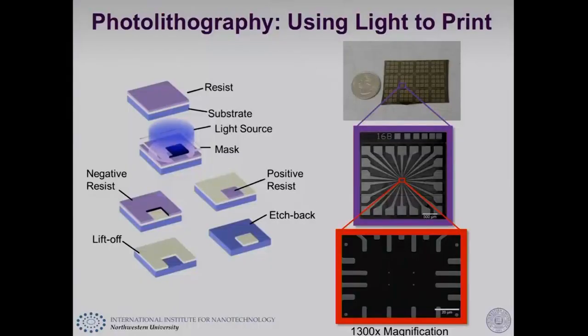So let's look at electronics and materials in general. Photolithography, a technique I think most people are familiar with to some extent. This is the way computer chips are made. Microfabrication and nanofabrication is done. The basic idea is you can create a mask. You can shine light through that mask over a substrate that's coated with some sort of polymer that's photosensitive, and that allows you to transfer a very intricate pattern to the underlying substrate. And then you can change the materials or the properties of, for example, the polymer coating that substrate. So you might make it insoluble, and therefore if you rinse away the unexposed area, leave the exposed area, you've transferred the pattern from the mask to the underlying substrate. Then you can chemically etch the underlying substrate, and that transfers then the pattern into that.